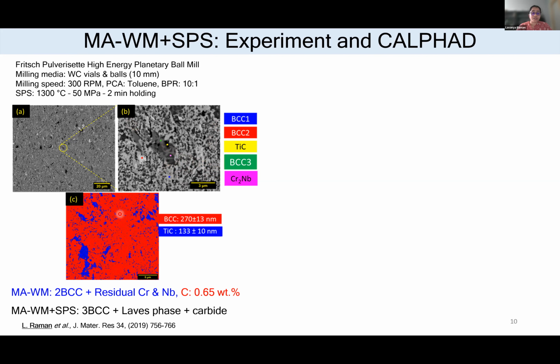When we tried EBSD to get the grain size, all these 3 BCC phases were indexed as 1 BCC. And we tried to validate the experimentally observed phase formation using CALPHAD. For that, the composition of the sintered sample was given as input along with the carbon content that we measured, so that we could see if we can predict the TiC formation as well.